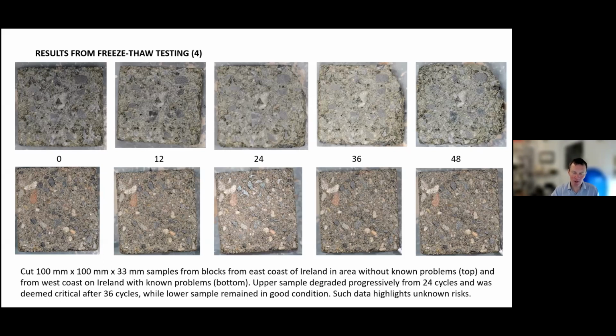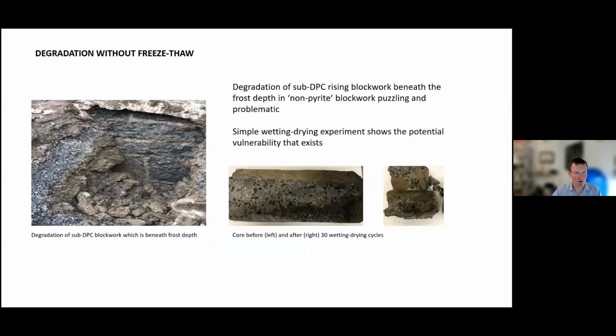So the technique can be used not only to help us understand the existing problems, but also what may perpetuate in the future. And my final bit of information about water is that it is possible to have degradation without freeze thaw. So this is an image supplied by Paul Quigley of some blockwork that is beneath the sub-DPC. So it is beneath frost depth, but it is heavily degraded. And this is a problem because when IS 465 was written, we believed that there would not be a large amount of degradation on sub-DPC because the blocks were stronger,